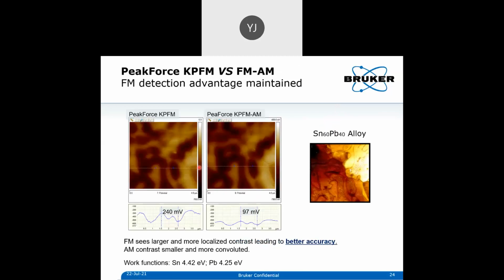And we also improve the accuracy by using the frequency modulation instead of the amplitude modulation. So here, you can see if you have the KPFM with the frequency modulation, you are basically looking at two different material, which is SN and PB. And we know theoretically the difference between them is about 240, 250 millivolts, the work function difference. Whereas if you use the AM technique, you only measure as 100 millivolts, which is not correct, right? Even though you see the contrast, the quantitative data is not accurate. So that's why we use the frequency modulation implementation to do that.